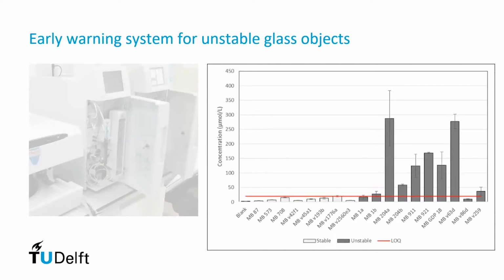So during my research, what we wanted to do was based on a question from a conservator. Can we actually identify unstable glass before it shows these signs of degradation? So the idea we had was, if we can identify the presence of these ions which have leached out of the glass, even though they are not visible, we may be able to identify unstable glasses, because not all glasses will show this behavior. It basically depends on their composition. And then when they are put in an unfavorable environment, the degradation will occur.